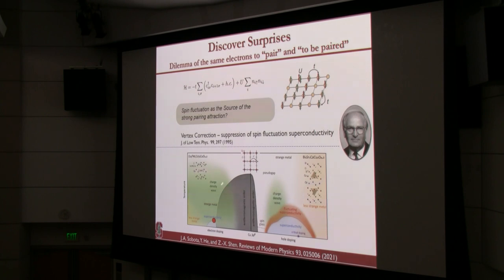This is a good system. Much of the effort is on the so-called hole-doped system, where TC is higher, with a rich phase diagram. The electron-doped system is interesting for this particular test because the antiferromagnetism is most robust. So that's what we set out to try to do.